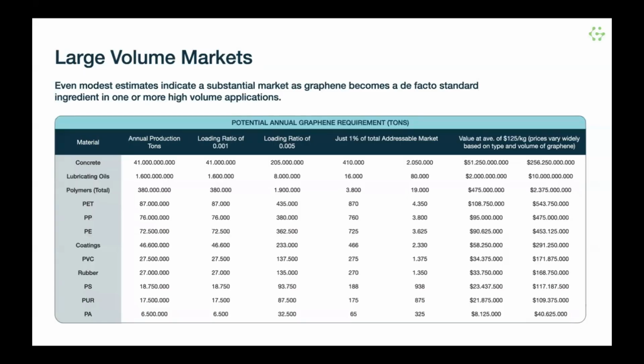Here are some very large markets that we have identified that graphene is being used in and has been proven to be effective as an additive to improve the performance. And we see that the demand potential for graphene is quite extensive. So these give some of the average market prices, and at the very low loading factors, because graphene can be used in some of these high volume markets, even at a very small percentage rate, the volumes and the dollar values of these markets is quite significant.